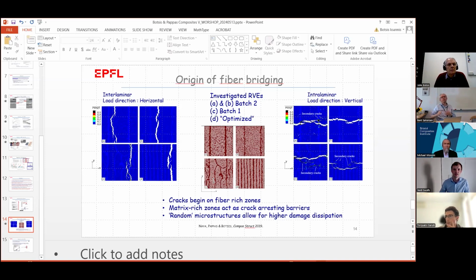We had a study some years ago where we used the same fiber, same resin, but different sizing, and a sizing that was not made for that particular resin we were using. And then we got a much weaker interface, and that resulted in, even though we were processing in the same way with filament winding and vacuum infusing the same way, much different fiber bridging coming out.